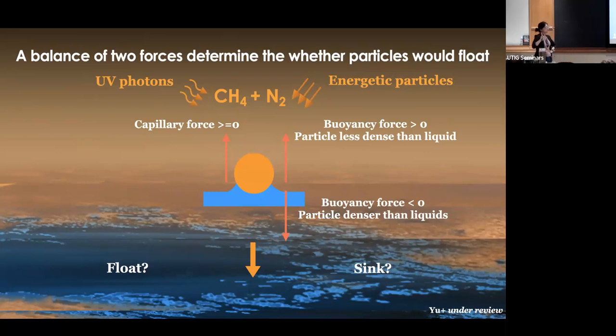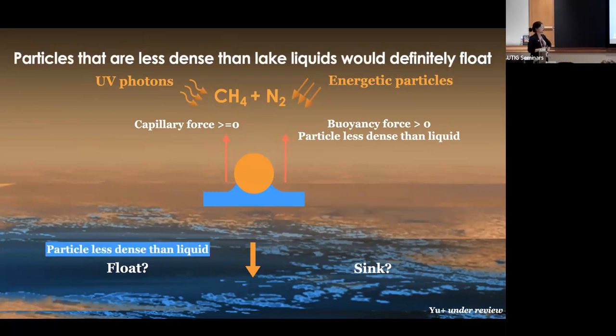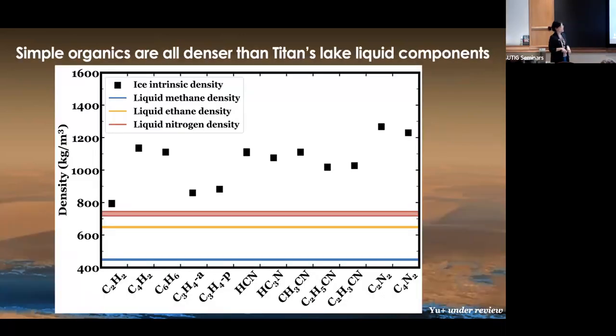So again, the first way to make things float is, if you have a particle that's less dense than liquid, you could potentially make it float, okay? So that's the first thing we explored, basically simply comparing the density of all these ices to the lake liquids of Titan, okay? And what we found is everything, of course, is denser than the lake liquids, because the lake liquid is methane, ethane, nitrogen. They're all pretty low density material.